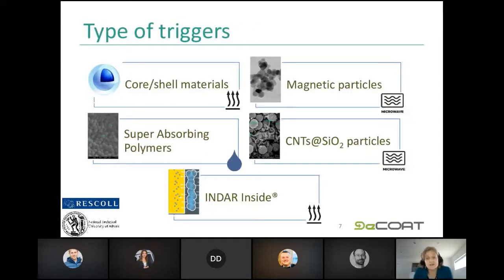So this is an overview of the different materials we are looking at in DECOAT. First one is a core-shell material. That means that you have some kind of capsule where the core can be liquefied when it's exposed to higher temperatures. And this will create an internal pressure, and at a certain point, the shell will weaken, the capsule will burst, and this will lubricate the coating a little bit, and hopefully we can release it after that. A second way is by putting superabsorbing polymers in capsule form into the primer layer. And when these come into contact with moisture, they will start to swell. And then we hope that we can have a separation in that way.